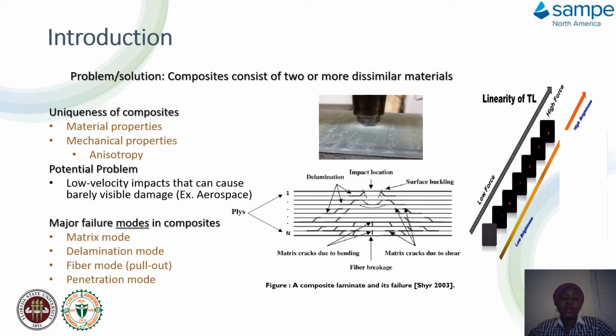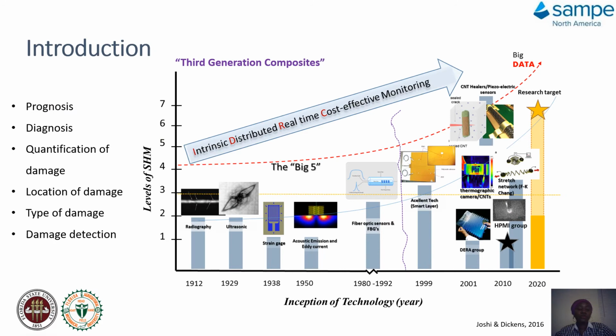But the problem now is how we can be able to get a good composite out without matrix mode failure, the delamination mode failure, the fiber mode, and the penetration mode. Some of the researchers have been able to use TL with composite material to show how light intensity is being exhibited from this material. And technology has shown that there is an increase in the multifunctional use of material in composites from 1912, and you can say a gradual process using it for radiography, ultrasonic, and continuously up to 2020.